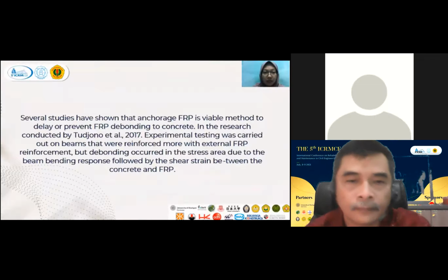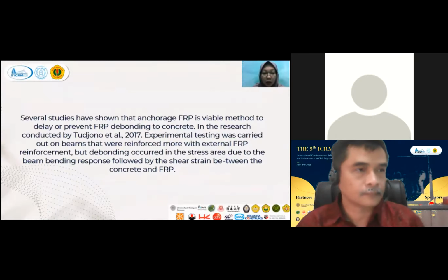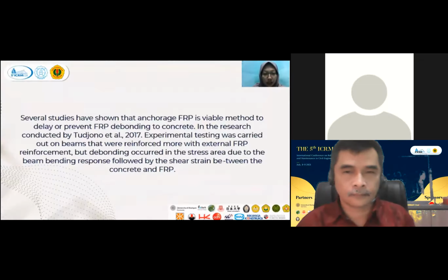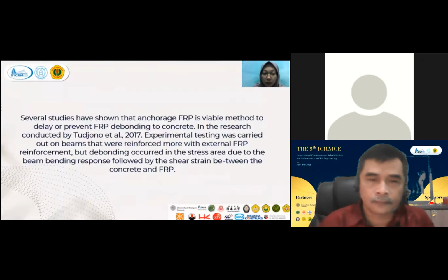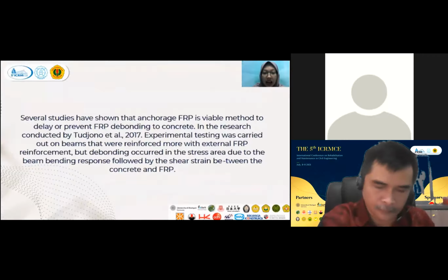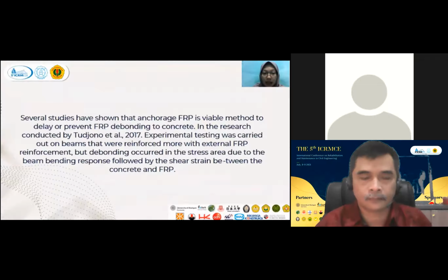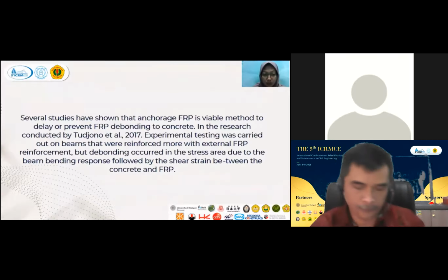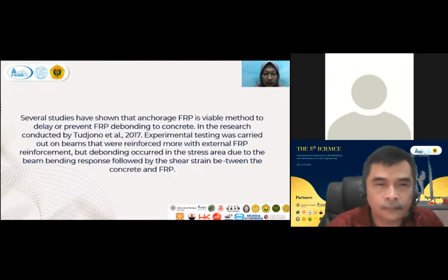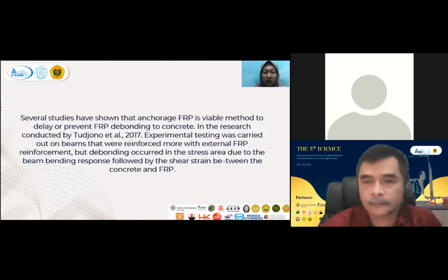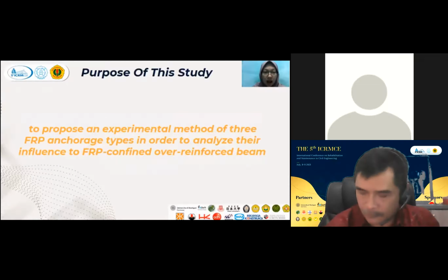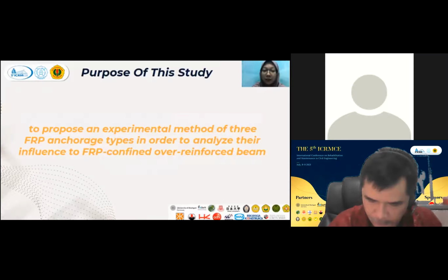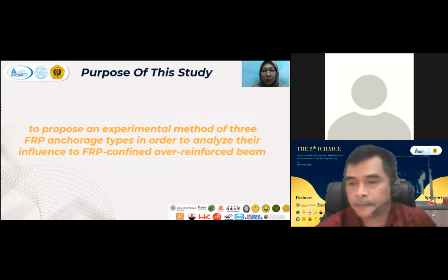Several studies have shown that FRP anchorage is a viable method to delay or prevent FRP debonding from concrete. In the research conducted by Tudjono et al., 2017, experimental testing was carried out on beams that were reinforced with external FRP reinforcement, but debonding occurred in the stress area due to the beam bending response followed by the shear strain between the concrete and FRP. The purpose of the study is to propose an experimental method of three FRP anchorage types in order to analyze their influence on FRP confinement over reinforced beams.